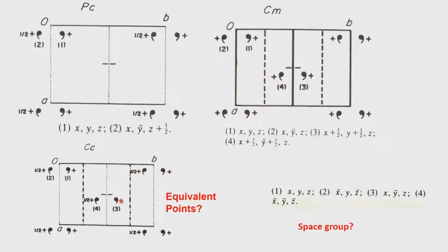So, the presence of the mirror can always invert a non-center symmetric or an asymmetric unit as well. So, what we have to look for is the fact that there is no x bar, y bar, z bar coordinate system in these 3 space groups, and therefore, these 3 space groups belong to the non-center symmetric space groups.